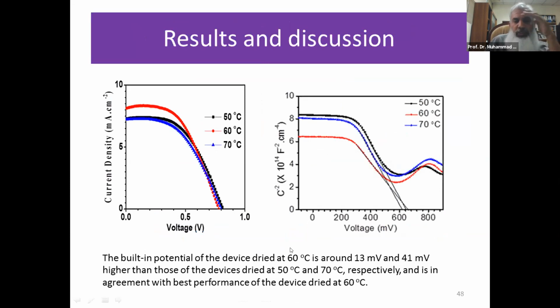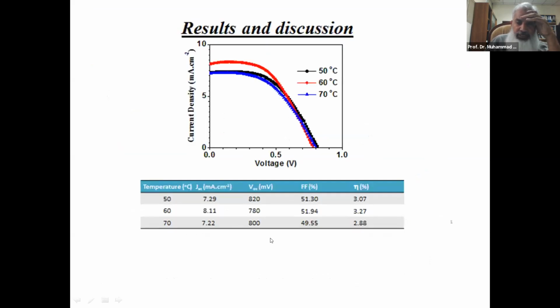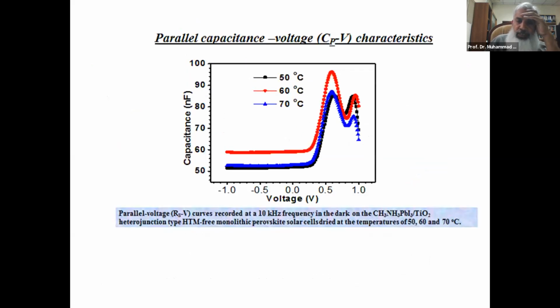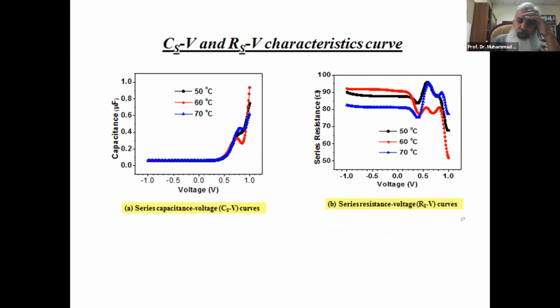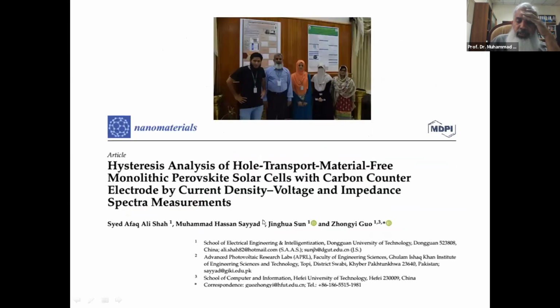So we confirmed this on the basis of IV and CV studies where Mott-Schottky analysis was carried out to show that the performance is highest at 60 degrees Celsius. So that's the table showing comparison of the photovoltaic performance at 3 different temperatures. And that was the impedance spectroscopy we carried out to compare that and provide charge transportation enhancement. Then recently we have carried out another study about hysteresis analysis.